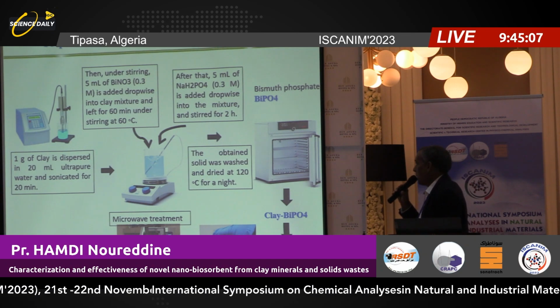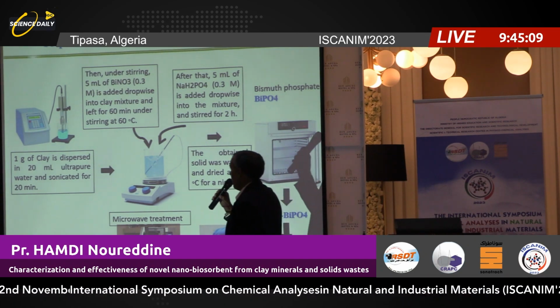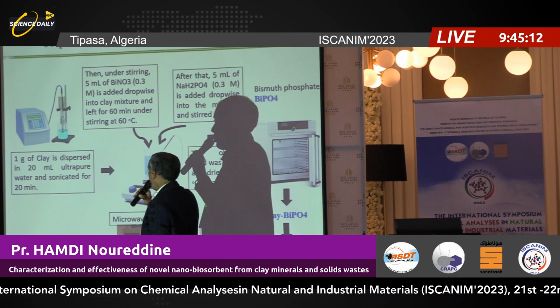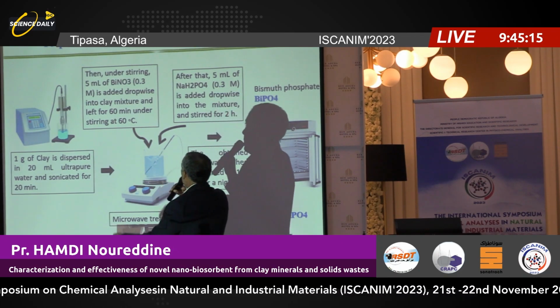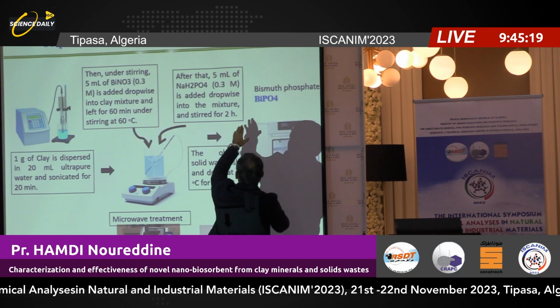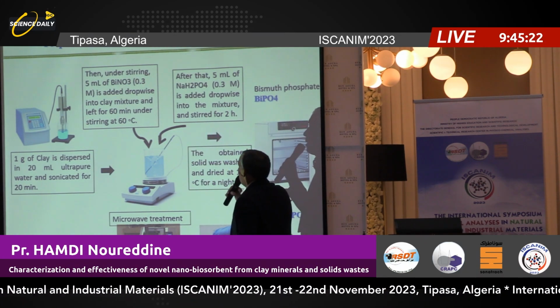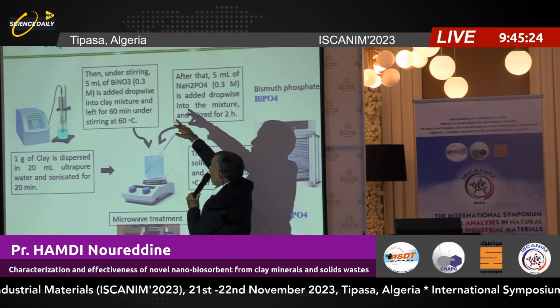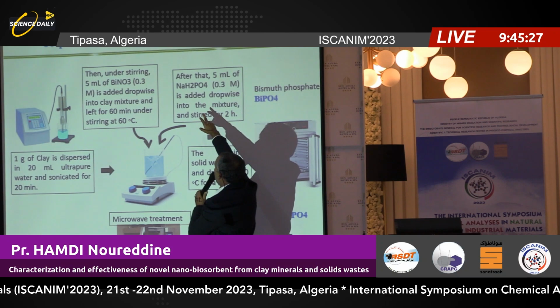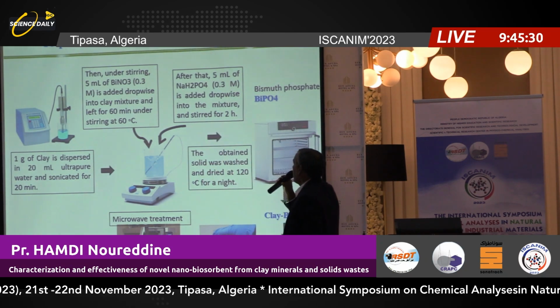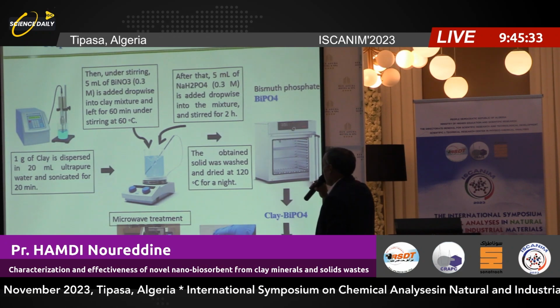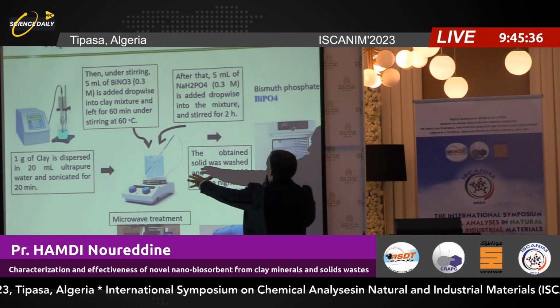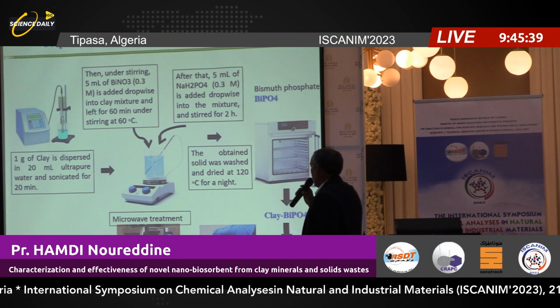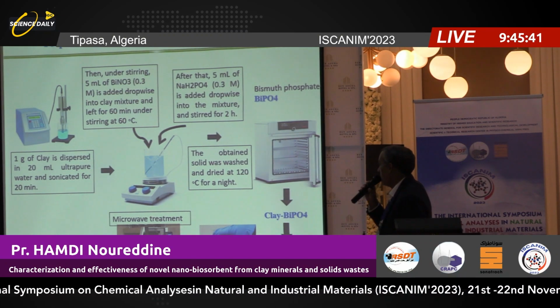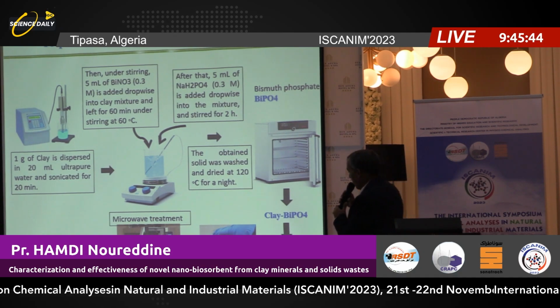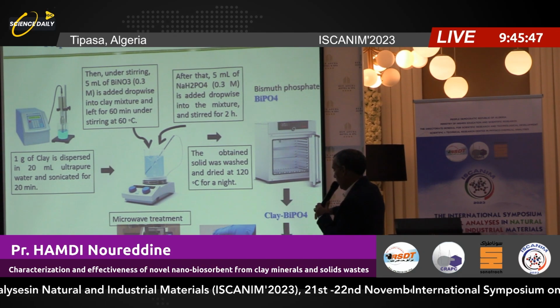For the synthesis process, firstly we sonicate the clay for 20 minutes. After that, we mix both components in order to obtain the bismuth phosphate: bismuth nitrate at 0.3 molar and sodium dihydrogen phosphate at the same concentration. After 2 hours, we put the solution in the oven at 120 degrees C for one night. We obtain the clay bismuth phosphate.